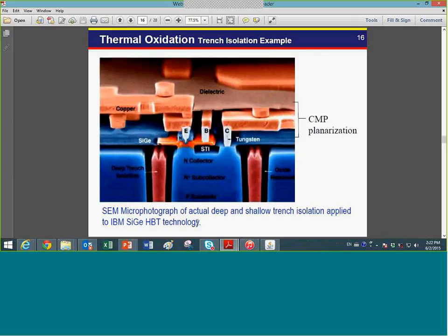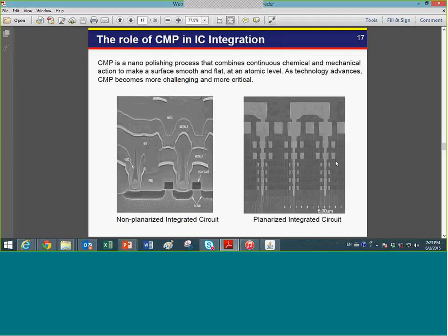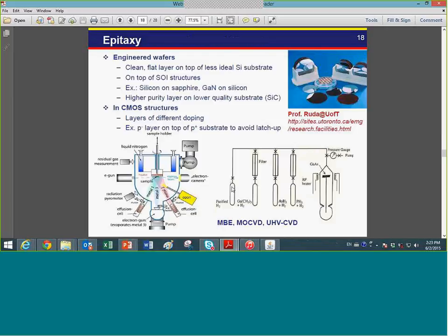This gives you the state-of-the-art silicon germanium HBT from IBM. You see the DTI and the STI here. The silicon germanium HBT is just here. All right, you can see from this comparison, this is without the CMP process, and this is with CMP. The CMP process allows you to build over 10 layers of interconnection on top of the silicon and still have high resolution in terms of lithography.